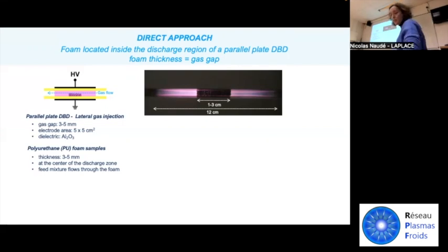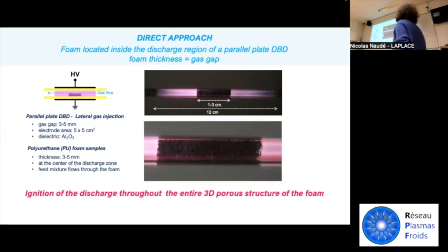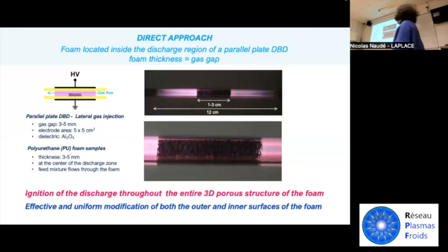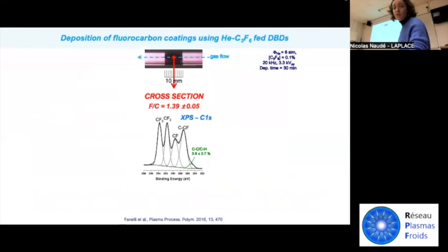By using this approach, we were able to obtain plasma ignition both outside the foam, but also throughout the entire three-dimensional porous structure of the foam. And this led to an effective and uniform modification of both the outer and inner surfaces of the foam.